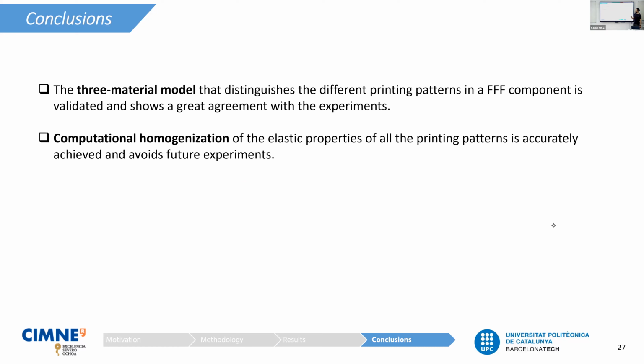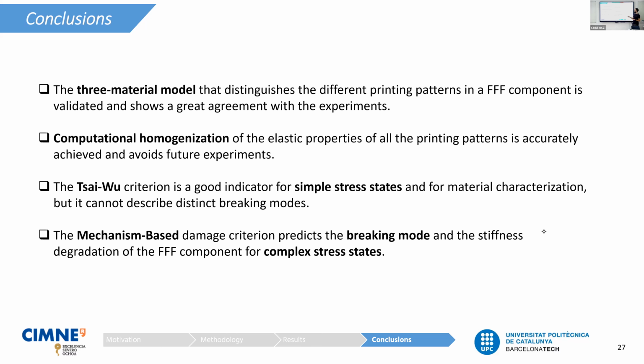Therefore, the main conclusion that we can draw is that, first of all, the 3 material model, meaning the printing pattern-based material model, is a proper characterization of these FFF components. Then also the computational homogenization is possible to be done with not only the inner but also the aligned and cross filaments. And finally, regarding the 2 damage criteria that were used, the Tsai-Wu criterion is a good indicator,